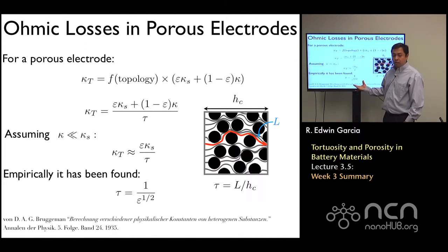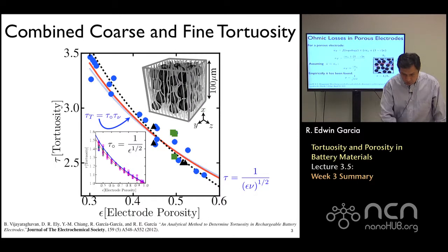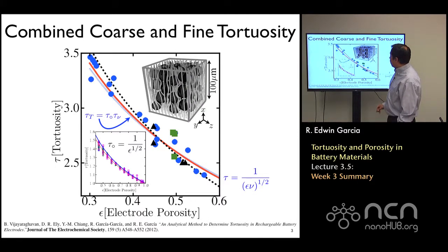We have used this relationship for many years, and as we move ahead and start detailing the response of the battery, what we find is that the response of the cell depends not only on the contributions to tortuosity because of those deviations around the individual particles, but also on the dispersion for the transport of matter in the electrode itself, which is not really a structureless medium, but actually could have binders, could have conductive graphite.